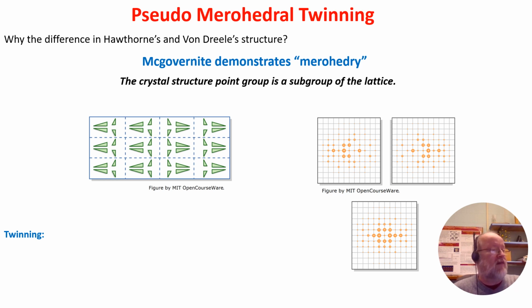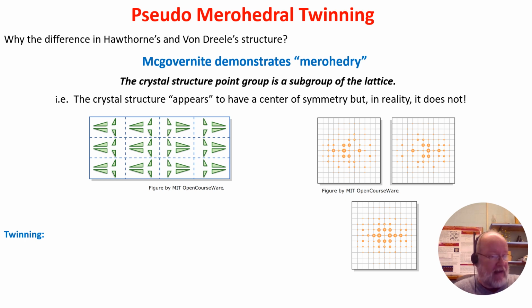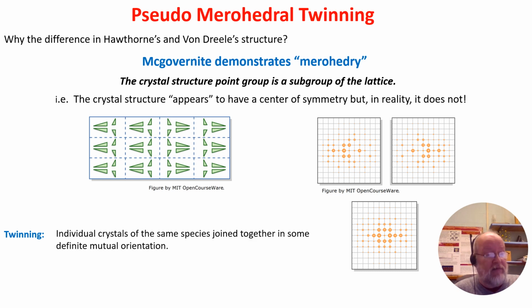That means the crystal structure point group is a subgroup of the lattice, or in our case, the crystal structure appears to have a center of symmetry, but in reality it doesn't. And that's because we're dealing with merohedral twins. In our case, pseudo-merohedral inverse twins.